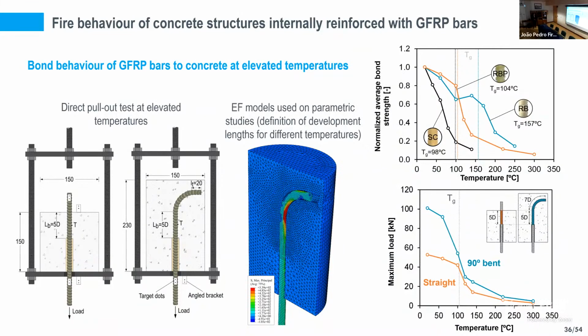Then we moved to the bond behavior of these bars to concrete at elevated temperature, where we did direct pull-out tests with different bar configurations. We also combined the experimental study with numerical simulations, and we were able to quantify the degradation of the bond strength of different types of bars with temperature, and also to provide, using numerical parametric studies, recommendations for the development length of these bars as a function of temperature and for different geometries.